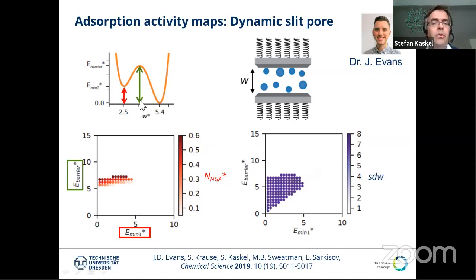And what he found is that there's a very narrow range basically of materials showing NGA in a general way. And it means basically that we need a certain ratio of the barrier to the energetic difference. And this was the outcome of this study. So in principle, it should be possible to observe this phenomenon starting from a certain bistability where there's a characteristic difference between the OP and the CP form, and should be topology independent. But of course, we have to take into account that the topology must allow for the structural transformation. And this is something that is at the moment more difficult to analyze, all the different topologies that can show the structural transformation. So we're still looking for new topologies that can also show NGA. And if you have a good suggestion, then we will certainly try it. Okay, thank you.